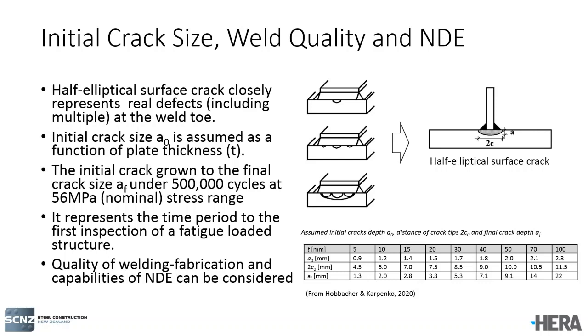So we know this crack, and this crack is being used for modeling, and the results are applicable to fatigue loaded structures like bridges. It equally can apply to seismically loaded structures, and it will not be a high cycle fatigue crack, but the crack is representative of low cycle fatigue damage in the case of seismic. Next slide.